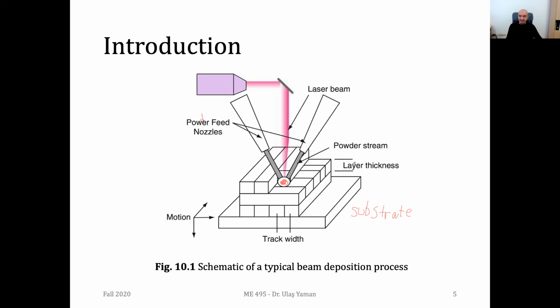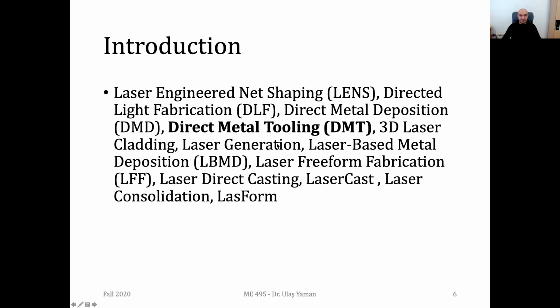And this is our layer thickness, and these layer thicknesses are quite higher compared to the other metal additive manufacturing systems. They're not around 100, but usually around 200 micrometers. And another thing you can see here is that they have different alternating patterns for each layer to make your part denser and stronger. They have, for instance, a vertical infill pattern for the first layer, then horizontal for the second layer, and vertical for the third layer. This is for increasing the density and the strength of the parts.